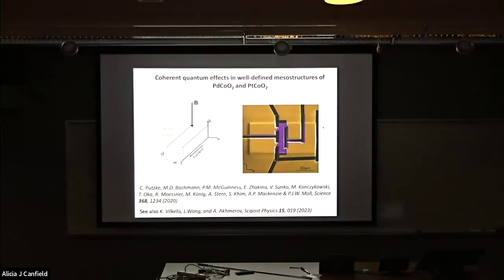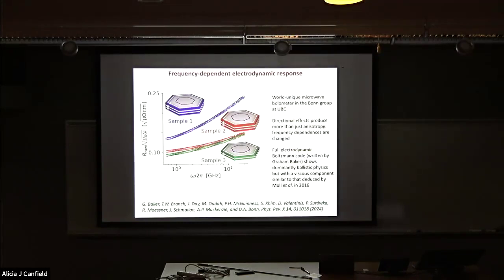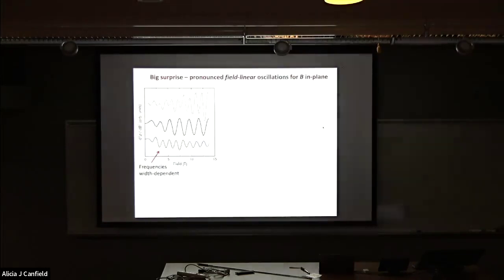And then because we had a field, Carsten Putzke and Maja Bachmann put the field on, and what they saw were really pronounced oscillations. The background's been subtracted here, but you see them with the naked eye. You see very pronounced oscillations in the C-axis conductivity as a function of field, and the frequencies that you're seeing are width dependent, and they are linear in magnetic field, not linear in reciprocal field.